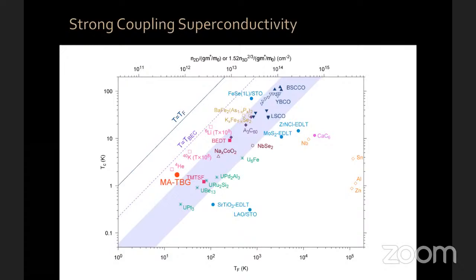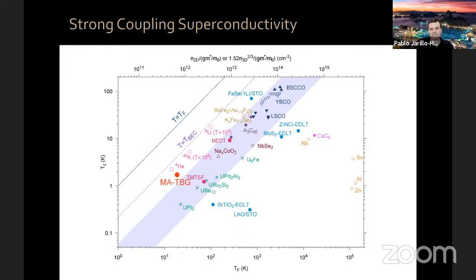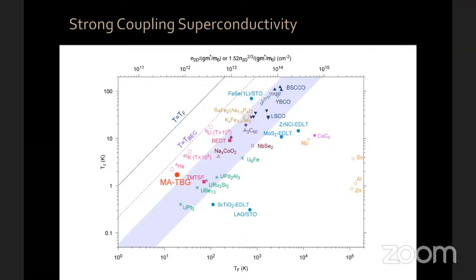You were talking, you have the flat bands. I understand they are more localized on the AA sites. And we believe this is where also you have the strongest electron-phonon coupling. In the previous times, people spoke a lot about the Kohn anomaly, and having this high density of states and activating the killing of the G band based on the electron-phonon creation, this would be an important effect localized at the AA sites. So do you have any clue or anything related to this aspect that could be behind this unusual superconductivity?